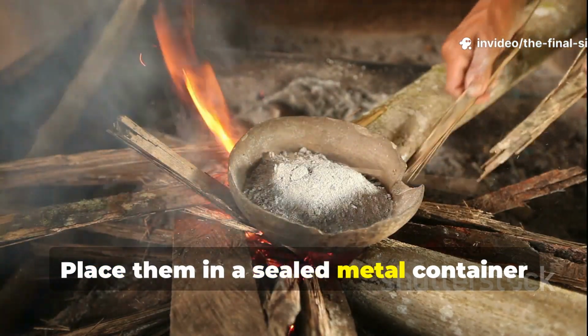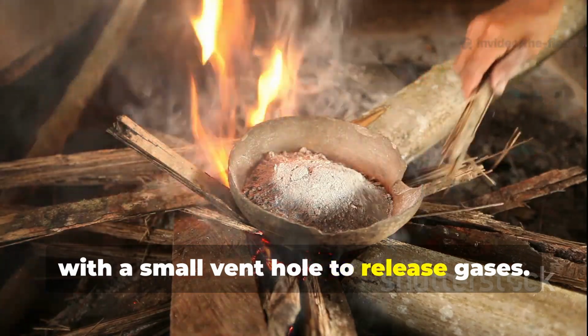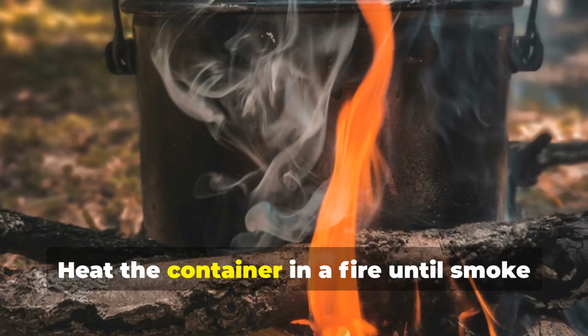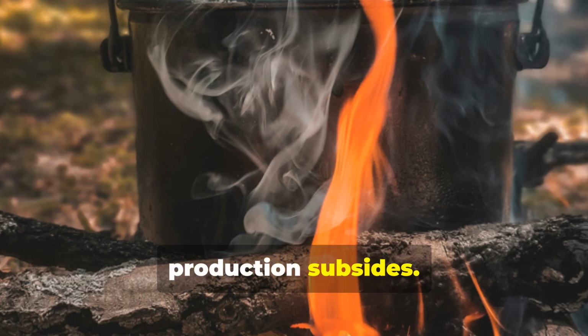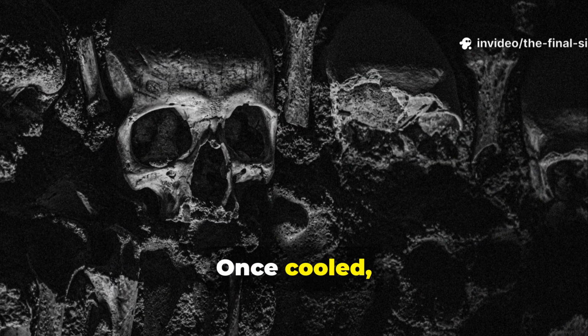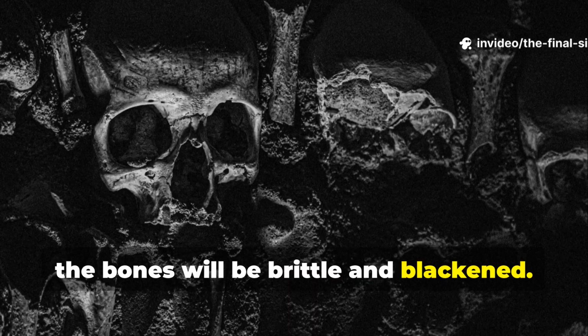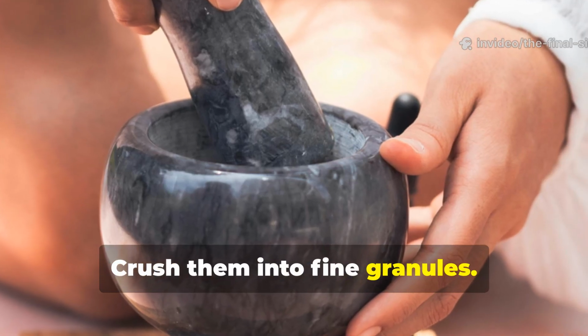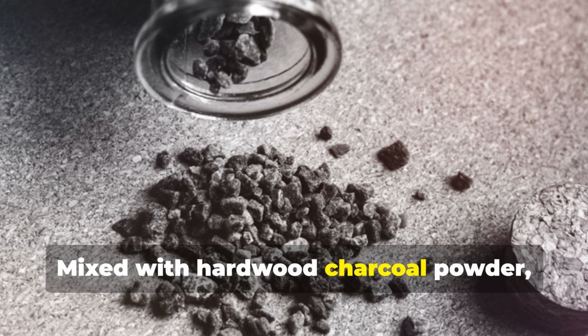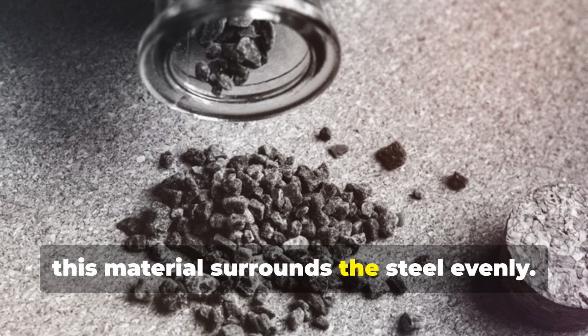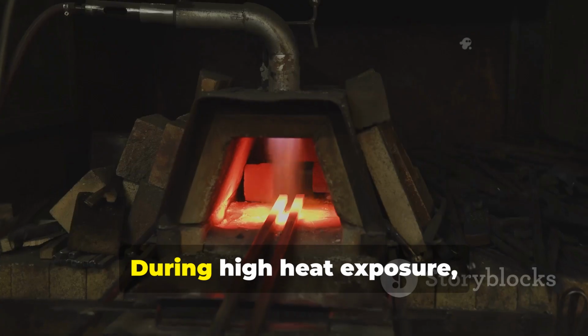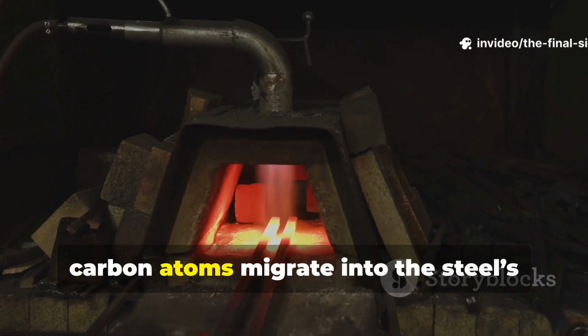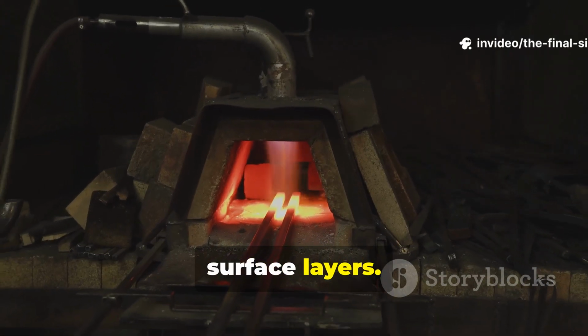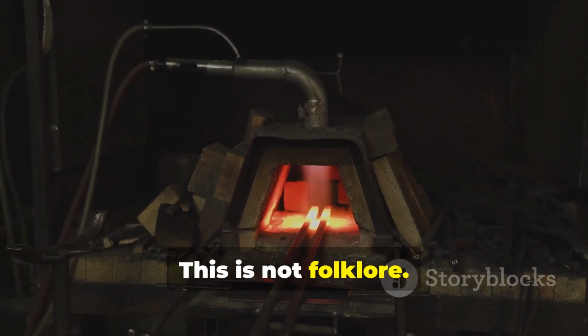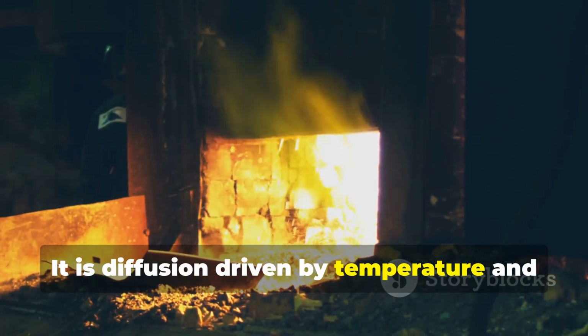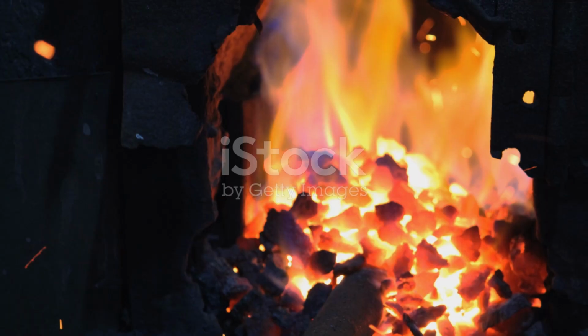Place them in a sealed metal container with a small vent hole to release gases. Heat the container in a fire until smoke production subsides. Once cooled, the bones will be brittle and blackened. Crush them into fine granules, mixed with hardwood charcoal powder. This material surrounds the steel evenly. During high heat exposure, carbon atoms migrate into the steel's surface layers. This is not folklore. It is diffusion driven by temperature and concentration gradients.